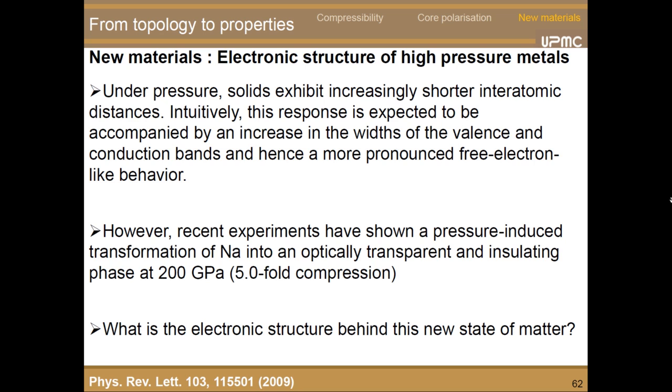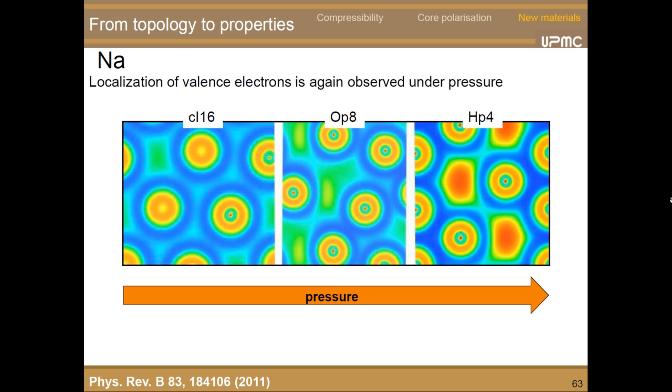And for that, we looked at the electron localization function, and with the input I've given you now, you can clearly see how at the beginning, when we have a metallic phase, we have here the cations, and we have this flat surface around it, which represents the sea of electrons. It starts localizing as we increase the pressure, and then when we go to the insulating phase, that's the neat structure we obtain. We have cations here, and that thing localized here, those are electrons. They're as localized as the cations. So basically, electrons from the valence have completely left the core. They have created new pseudo-cores, which behave like anions in our system, but with no core inside.